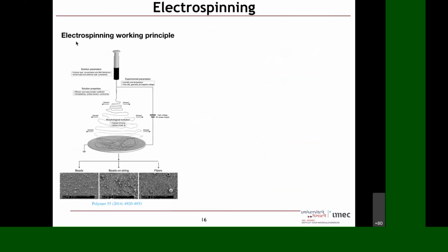So I'll slightly deviate here and tell you what is electrospinning, what can we do and so on. But again, mostly the idea is to show you, once you have the idea, how you can proceed when you're doing research. So how electrospinning works, as I told, you put a polymer solution here, mix polymer in water or DMF or something like that, nicely let it dissolve, you slowly push the solution, you put a high voltage between the top needle and the bottom plate, and the electric force is so high that you have to go to very high electric fields like 20, 30 kilovolts. So you have a very high electrical gradient here that pulls the polymer solution out.